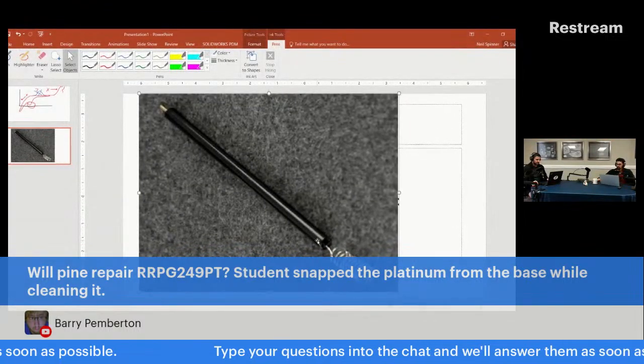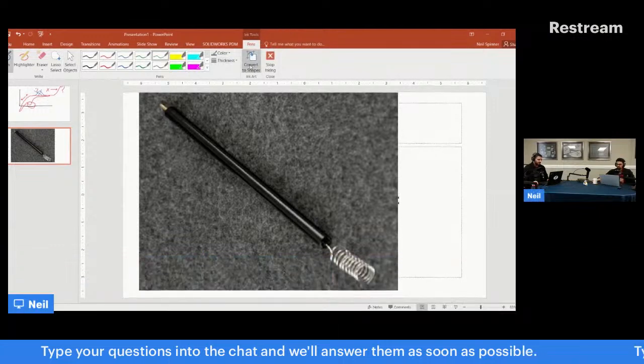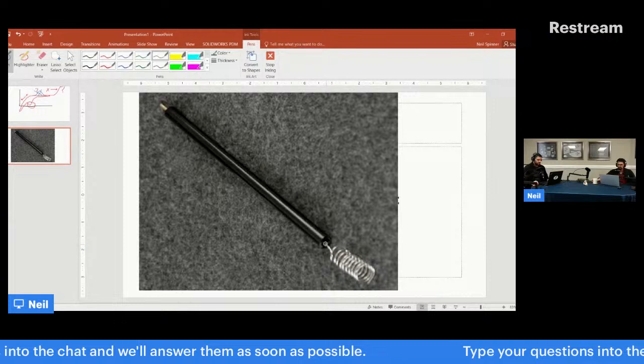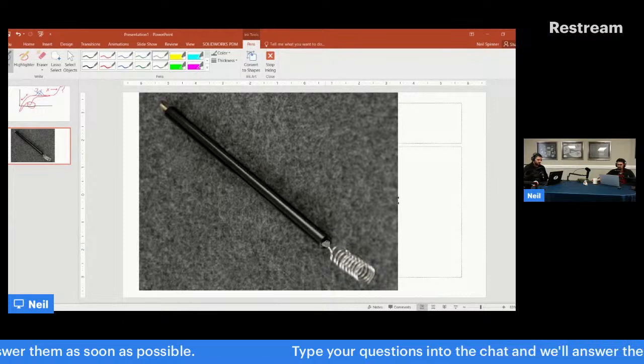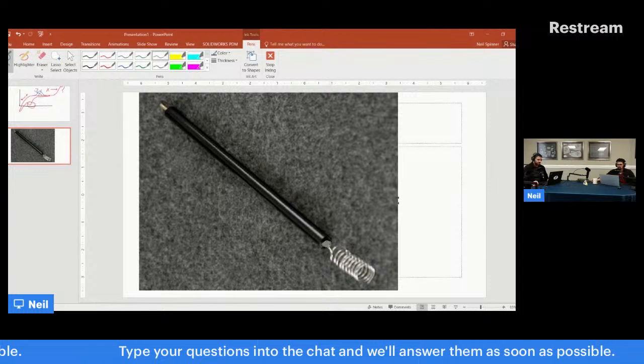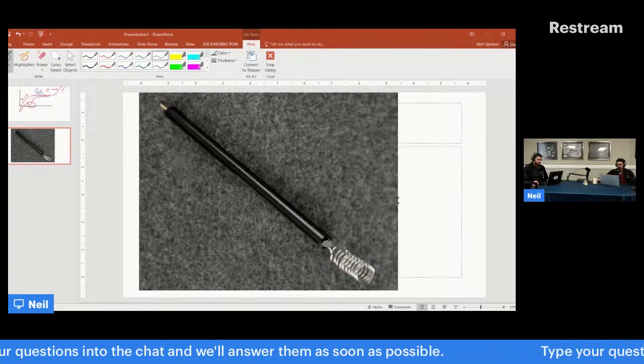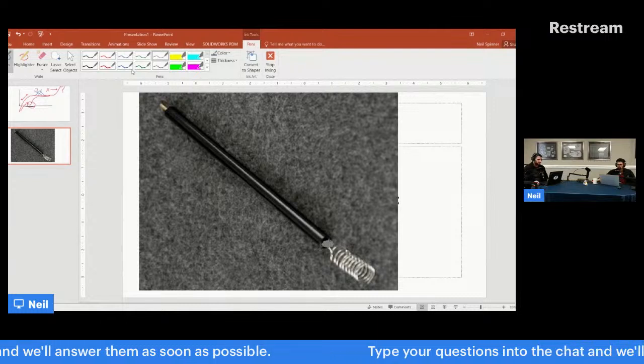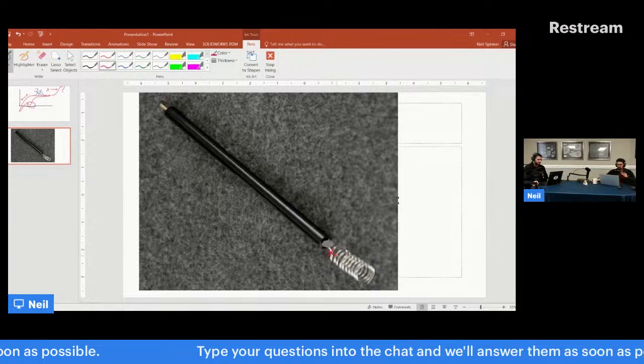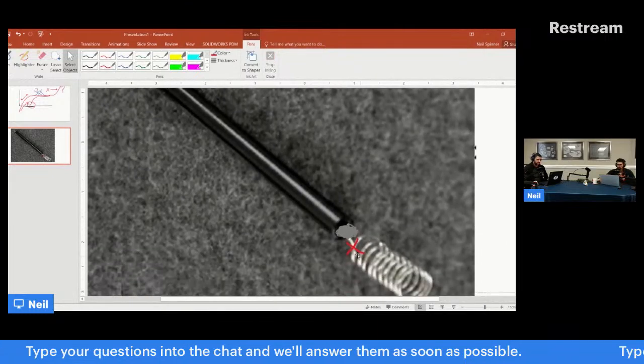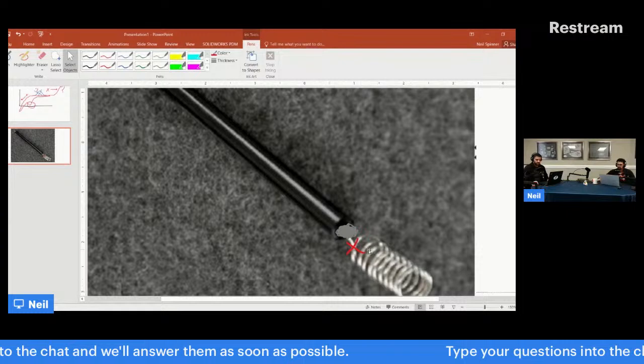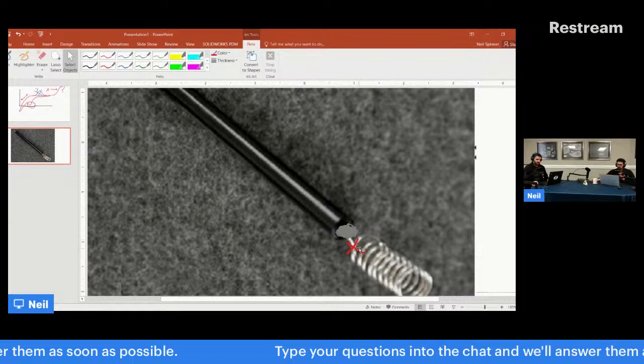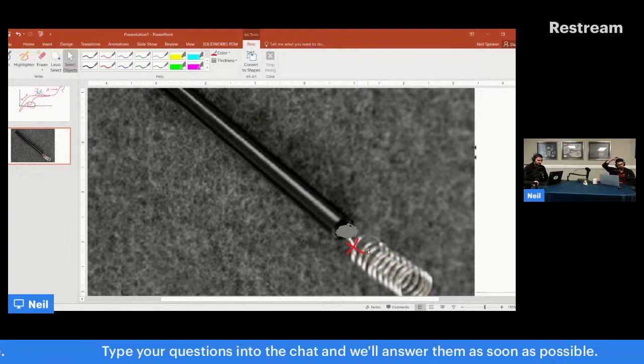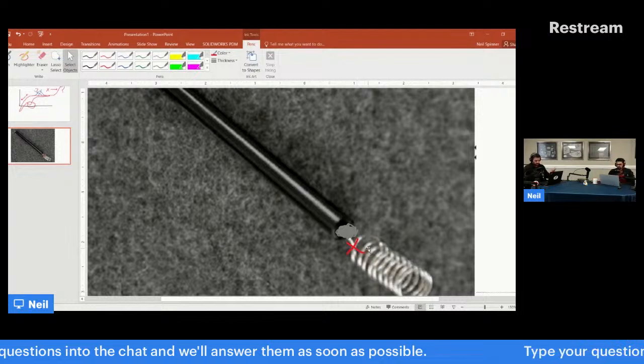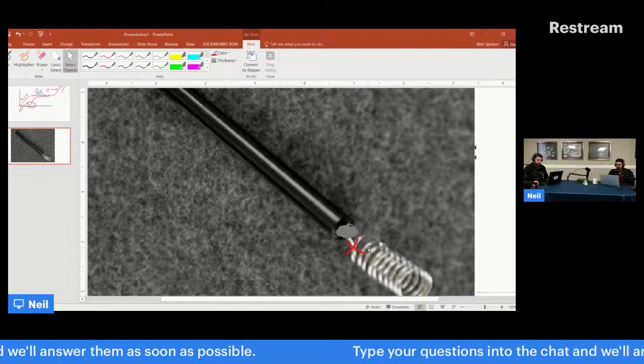So all I wanted to point out was that this is the platinum counter electrode, and actually what we have in our current models is down at the bottom here. I'm drawing it in gray because I don't have white. Is like a Teflon sort of plug, right? Mm-hmm. And so most of the time when these break, they break down here, because this is the part where it's weakest. It curves, and a lot of times when people are cleaning it, it fractures right here, unfortunately. It's somewhat of a consequence. It's platinum, it bends, and then it eventually can get weaker.